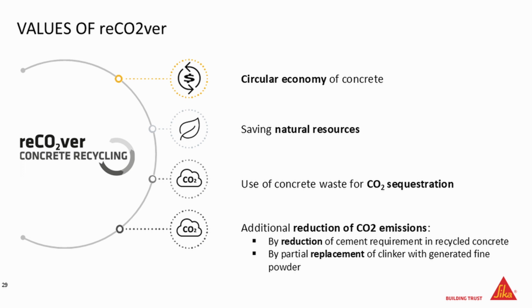So basically we can create with this a circular economy of concrete. We are saving natural resources because we are taking out the aggregates again from the concrete. We can use this process for CO2 sequestration, so bind CO2 into that. And with that, we can reduce the cement fraction of the recycled concrete, and we can also use the powder to partly replace cement. So that maybe sounds nice, and you would ask, okay, does it really work? So we asked ourselves, does it really work?